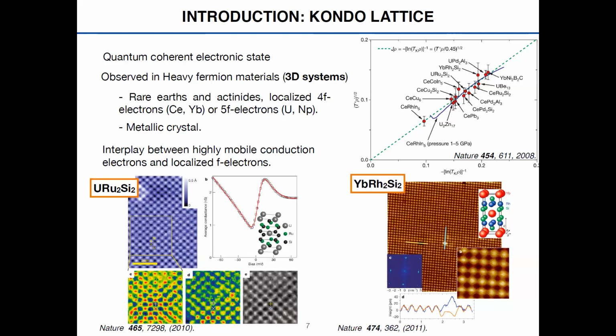As you can see, they all contain either rare earth elements or actinides that have these localized electrons in their 4f or 5f orbitals. So you can picture these systems as a lattice of magnetic impurities, because of these rare earth or actinide elements, embedded in a metallic crystal. Two examples are here, with uranium and with ytterbium. Basically the strong electron correlation physics that appears in this system is due to the interaction between the magnetic moments of these localized electrons and the highly mobile or itinerant electrons of the metal.